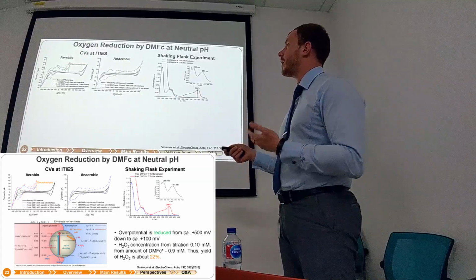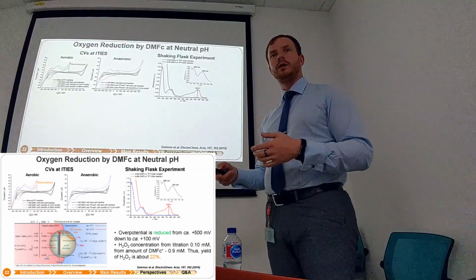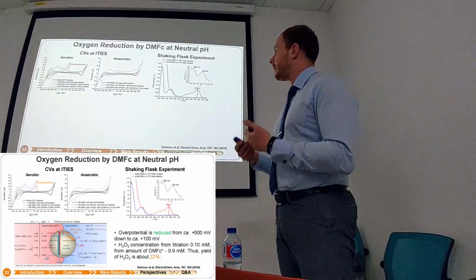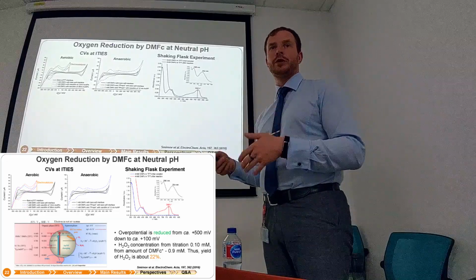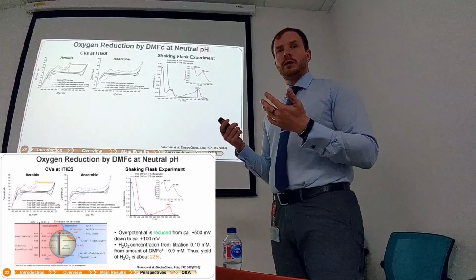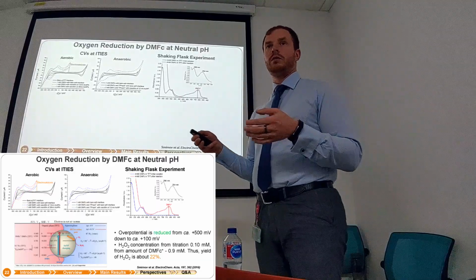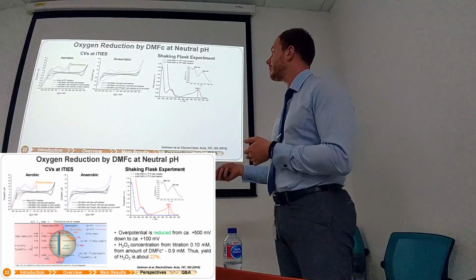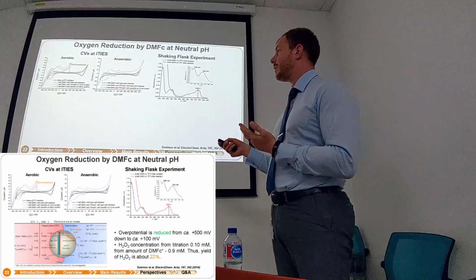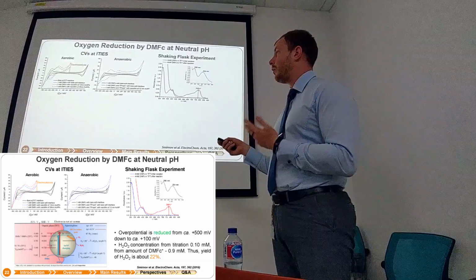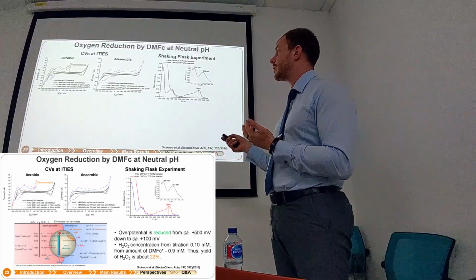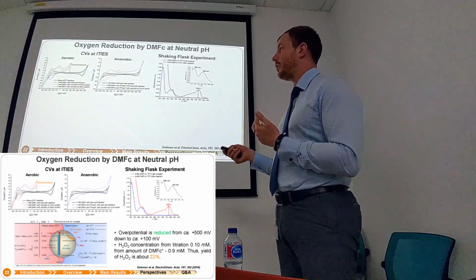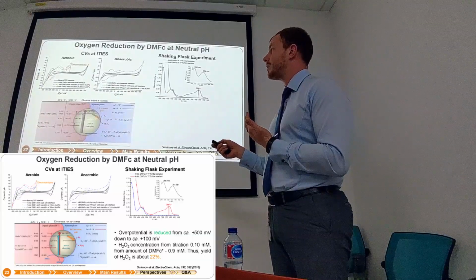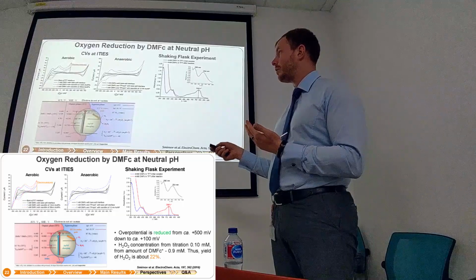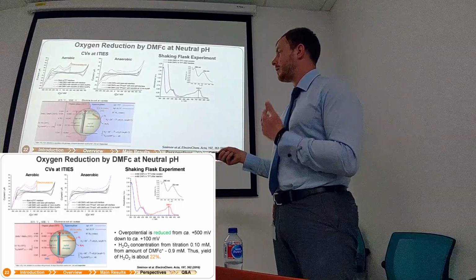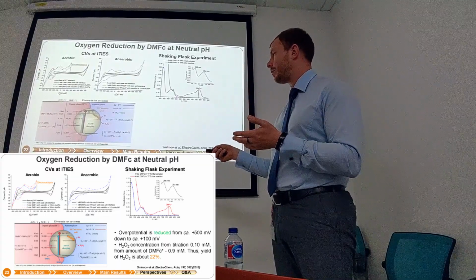And coming back to the application, we changed ferrocene to a much stronger donor, decamethylferrocene. And decamethylferrocene is known to reduce oxygen to peroxide or to water. The problem is that it happens on a half an hour, half a day or 1 day timescale. But what we did simply was CVs with and without film, in aerobic and anaerobic conditions, and we came to the conclusion that this is an ongoing electrocatalytic wave, because there is no reverse wave.